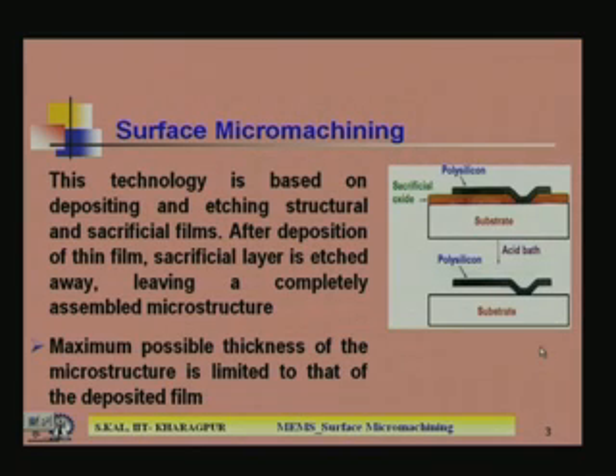Now, in surface micromachining, here you can see some diagrams which explain how we can go for surface micromachining structures. It is basically based on depositing and etching structural and sacrificial films. After deposition of the thin film, the sacrificial layer is etched away, leaving a completely assembled microstructure. The maximum possible thickness of the microstructure is limited to that of the deposited film. So, now let me explain a little bit based on this figure.